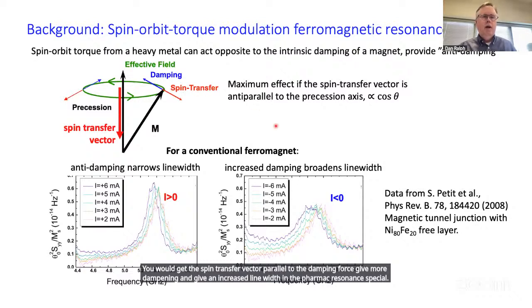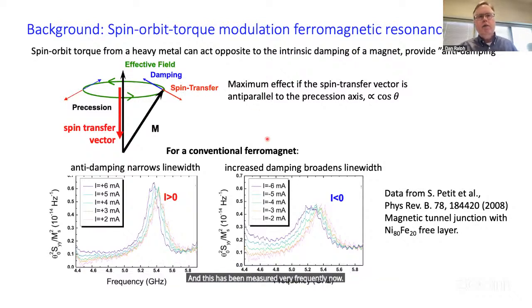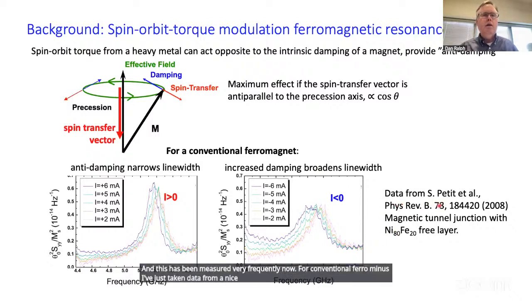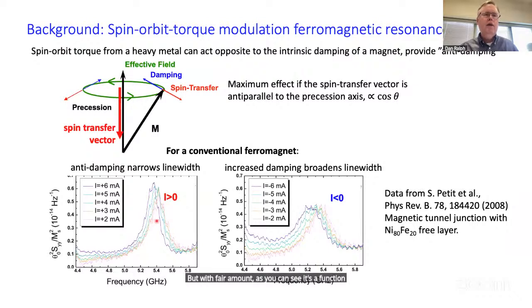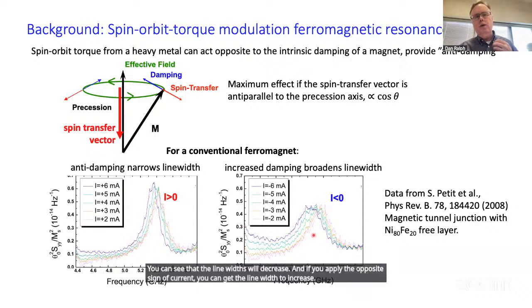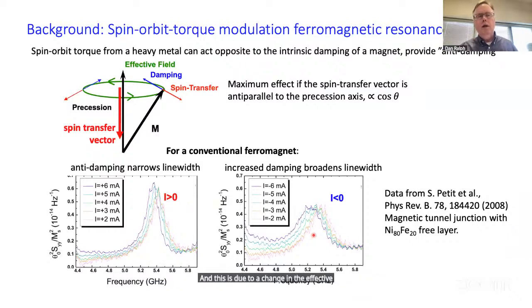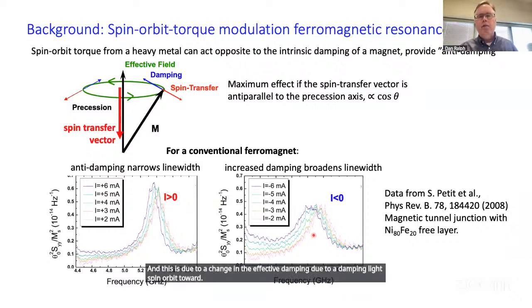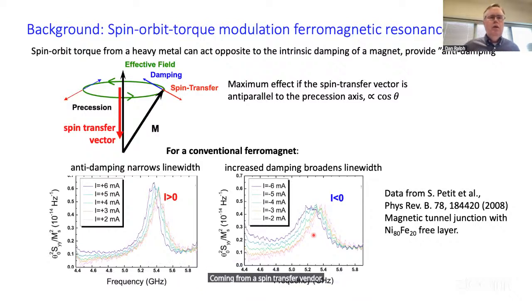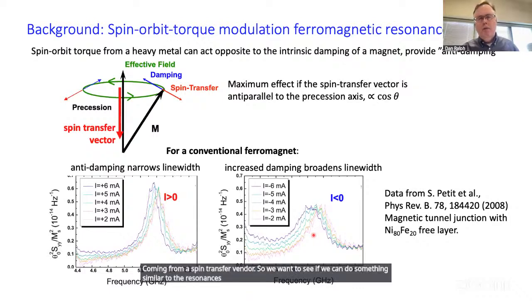And this has been measured very frequently now for conventional ferromagnets. And I've just taken data from a nice paper by S. Petit here from 17 years ago now. But with ferromagnets, you can see as a function of one sign of current that the line width will decrease. And if you apply the opposite sign of current, you can get the line width to increase. And this is due to a change in the effective damping due to a damping-like spin orbit torque coming from a spin transfer vector. So we want to see if we can do something similar to the resonances in our chromium sulfur bromide.